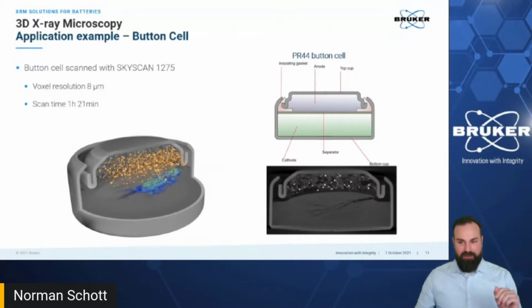So our first example is a button cell, and what we are seeing here is an anode, in the bottom area is a cathode, and in the middle is a separator. And what we can see in this data set is, of course, the metal housing. We can see that the anode contains high dense particles because of the high density, also some air inclusions and low dense grains. The cathode has a massive crack, and all these features we can analyze.